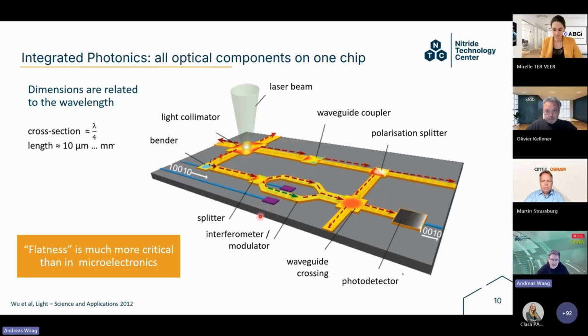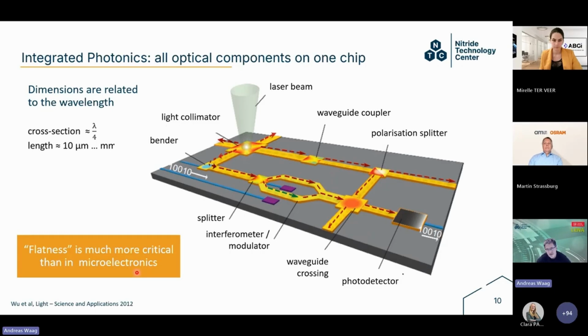For such devices concerning dimensions, they are on the order of a wavelength quarter, usually in the cross-section, to lead to an efficient waveguide. So we are talking about dimensions depending on wavelength on the order of 100 to 300 nanometers. So that's not so small in comparison to microelectronics. However, the flatness of these structures plays a much more critical role than in microelectronics. And the reason for that is that we are dealing here with electromagnetic waves, which have a portion running outside of the waveguide, so they are penetrating into the environment, and therefore they feel much stronger the surfaces and also the environment of these waveguides.